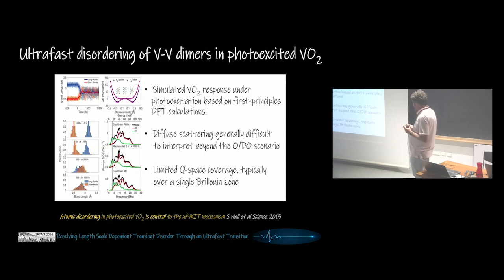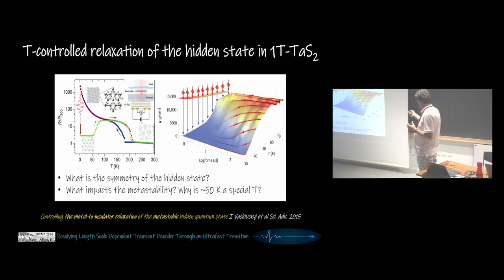Now, the problem with this is that, number one, you're assessing information over a very limited Q-space range. And number two, it's a bit shaky how to interpret the data. What does it mean, what you see? A simulated vanadium dioxide response was done in this work based on first principles DFT calculations. And as I said, diffuse scattering is generally difficult to interpret beyond this simple-minded order-disorder scenario. Okay, so that being said, let me get back to 1T tantalum disulfide.